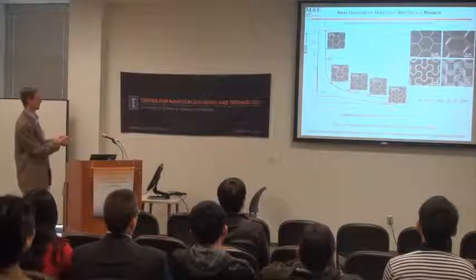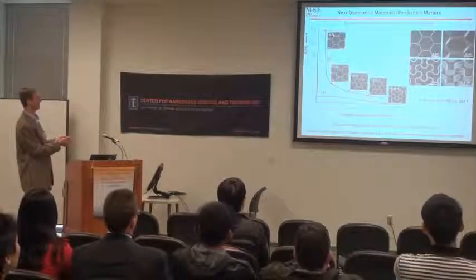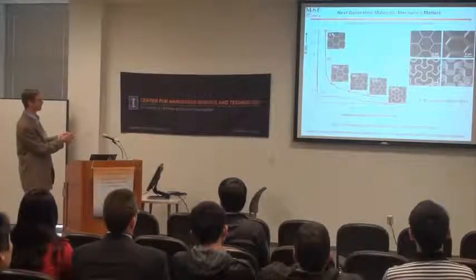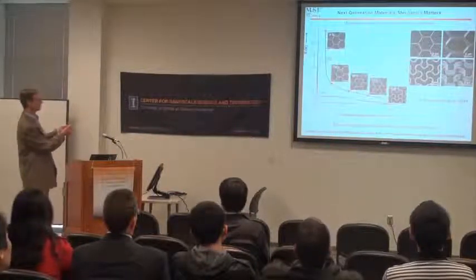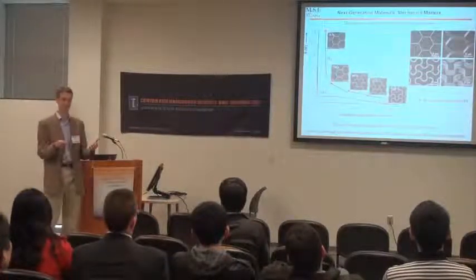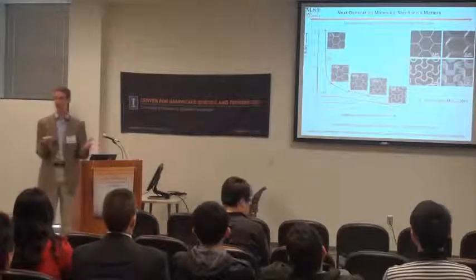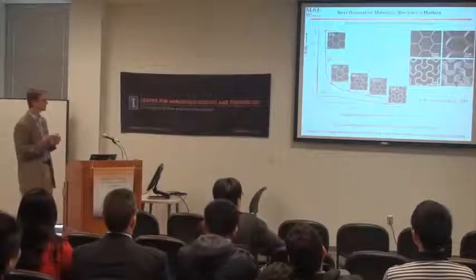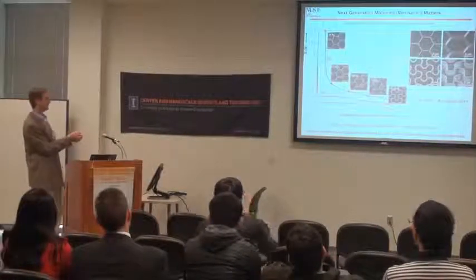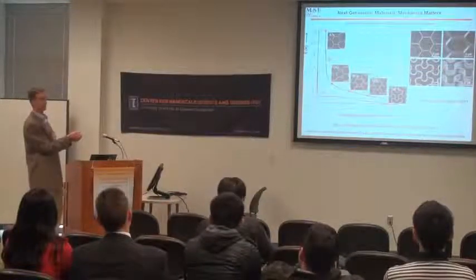A number of groups, and this is a paper that Peter Notten and his group at Eindhoven published a year or so ago, make the silicon in a honeycomb structure, and so it simply buckles and comes back. It reversibly undergoes buckling and contraction, and that handles the strain. Why silicon? It stores 10 times more energy than carbon per unit volume. There's another issue: it reacts with the electrolyte and forms a polymer film on the surface, and it turns out that polymer film gets cracked when it expands and contracts.